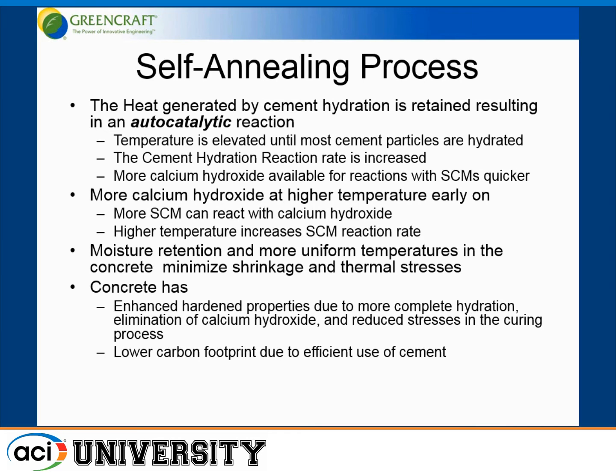Then more calcium hydroxide at higher temperature early on will cause the SCMs to react, and reacting at higher temperature will increase the SCM reaction rate. Doing this while we're maintaining the moisture and a more uniform temperature in the concrete minimizes shrinkage and thermal stresses.